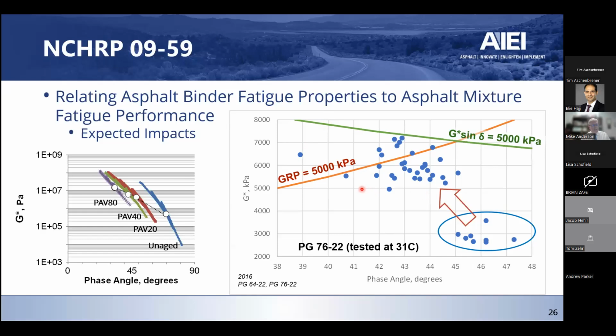The other thing to note is, as these are 76-22s tested at 31 degrees C, if we test them at more appropriate climatic temperatures, like 25 degrees C, which would be about appropriate for Kentucky, we would expect the data to move up and into this group here. So it moves lower right to upper left, and it follows a similar shape, not quite the same, to what we would see with aging. And I think it moves in this direction.